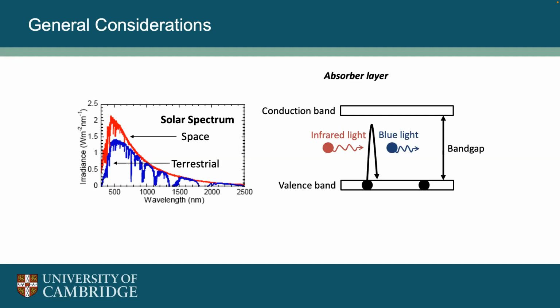But if we come in with blue light, higher energy light, we can energize well and truly above the band gap and energize electrons and holes, which we can then collect at the electrodes. Just as a note here, though, because we've given it excess energy, all of this energy is lost to heat, because these electrons are excited to high energy states, and then it relaxes down, and we lose some energy to heat. So there's inevitably some losses in this process to be able to harvest as many photons as we can. I'll speak about that just now.